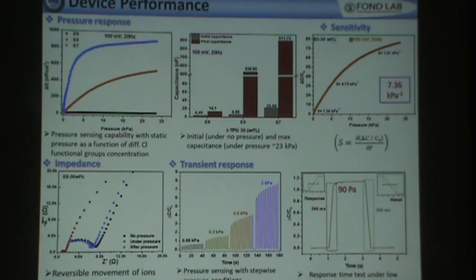And then from the transient response, you can see that our device can adapt to different pressure conditions. We can also see from the graph here that at lower voltage as well as at lower pressure, we can actually detect the response as well as the reset value of our system.